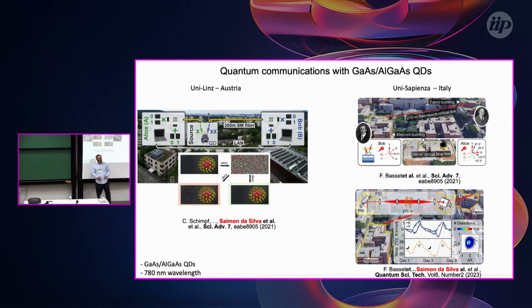But at this time, Rinaldo Trotta was just moving from Linz to Sapienza University, and there was a competition between Linz and Sapienza to see who did the experiment first. In the end, they did it at the same time and published in different journals at the same time. But the message is basically that these gallium arsenide quantum dots have good optical quality that you can use for quantum key distribution.